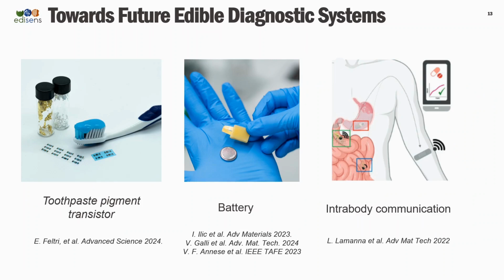So to wrap up, in a provocative way, we have used Haribo gummy bears instead of gelatin to show that actual food can be used to create devices. And we have used it with activated carbon to create a conductor that you can use, for example, for resistive sensing, which can be strain, temperature, pressure, but we have also shown it in a field effect transistor. But that is only one of the devices that we make. As I mentioned before, we have just published a paper where we use a pigment from toothpaste for edible transistors.